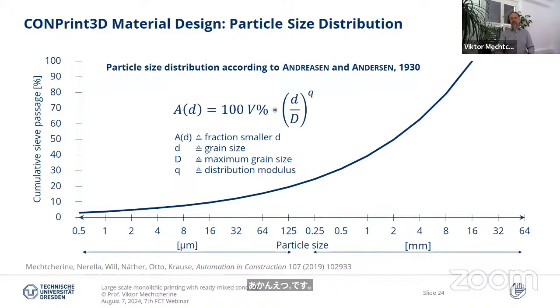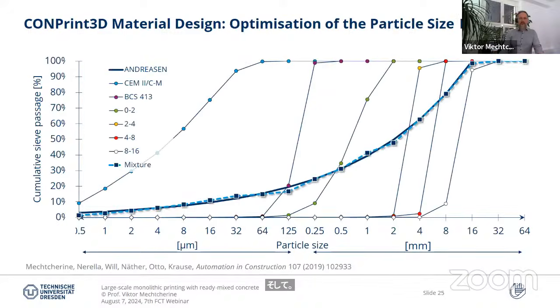And how to get it? You probably all know this. It's about choosing the ingredients for the mixture in such a way that, by applying some quantity of these different materials, and actually we start already with cement, not just with aggregate, cement, and then in this case some pretty fine powder, so stone powder, limestone powder, etc. And then we have two different sands, and then we go to larger aggregates. Good. You see that in this case, we could match the shape of the curve pretty nicely.